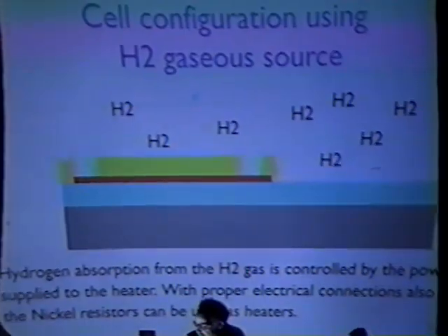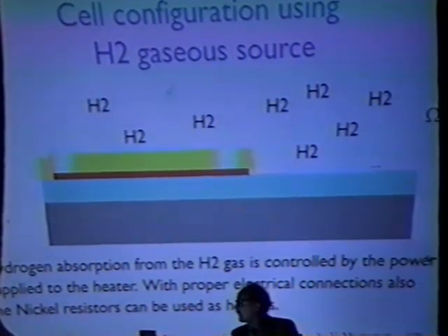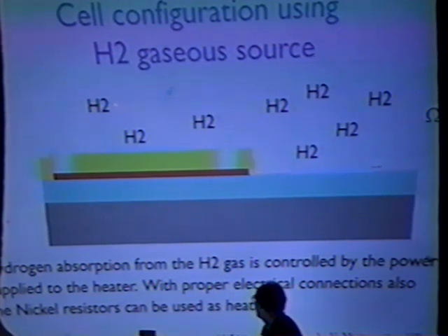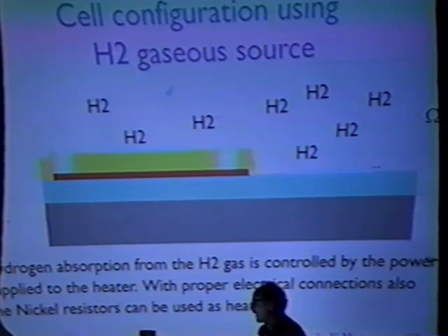Just to confirm that it was the hydrogen loading from the solid source, I made some experiments using hydrogen in the chamber. In this case, I was forced to use higher power because the pressure of hydrogen outside the cell decreases a lot the thermal resistance of the cell.